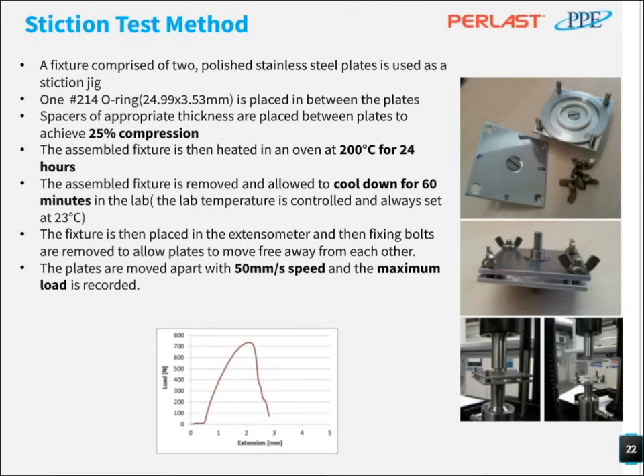And then we take the jig out the next day, cool it down for 1 hour, and connect it to our tensometer and remove the bolts. In tensometer, we measure the maximum force to remove the plates away from each other. In the bottom graph, you can see what kind of profile we get, and as you can see, we take the highest maximum force, the peak value, as the stiction force.